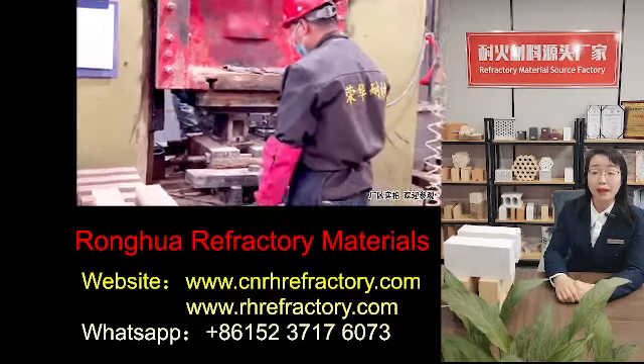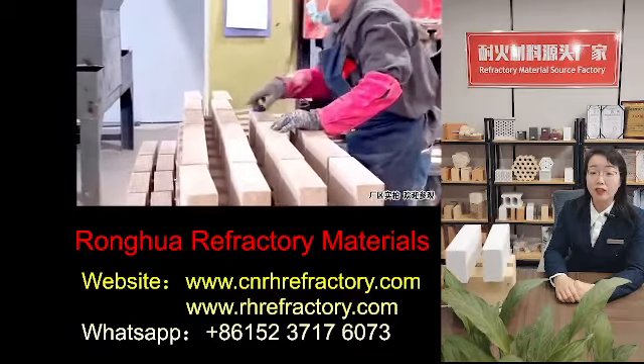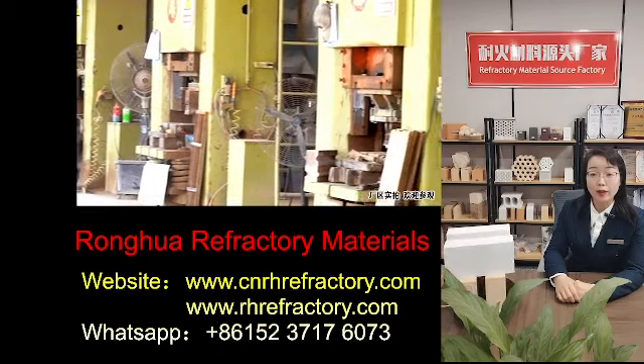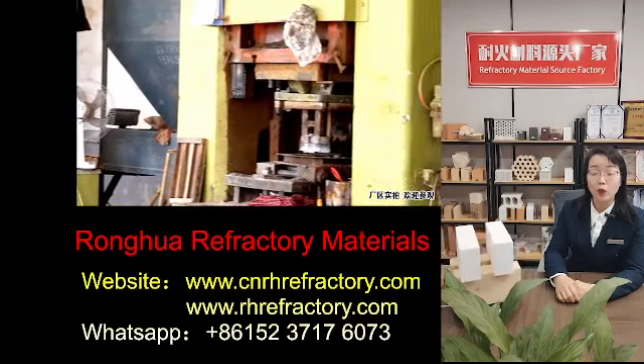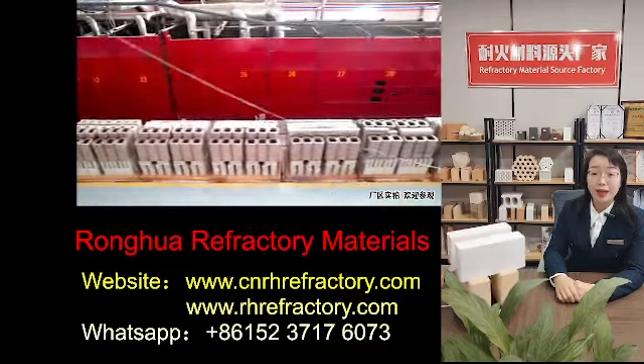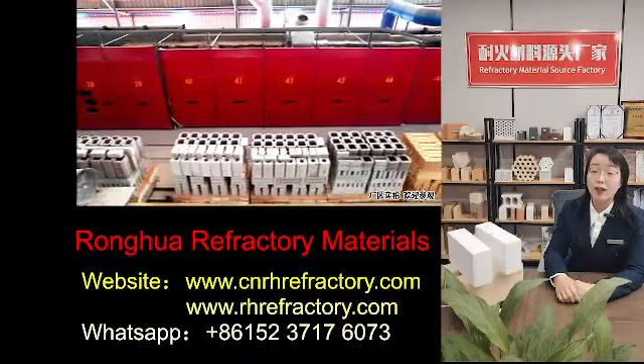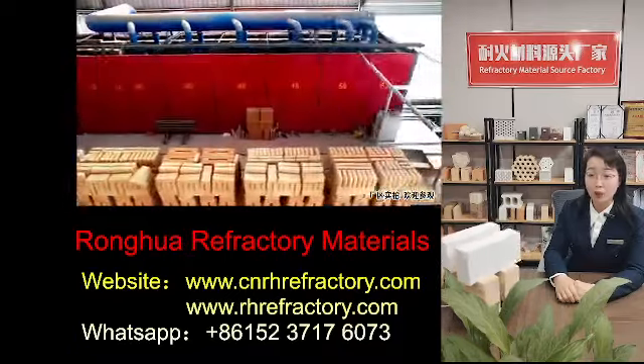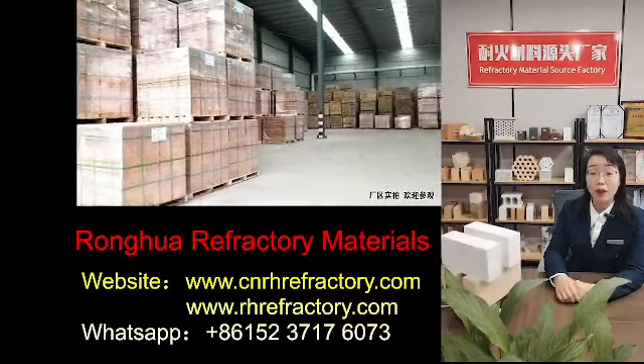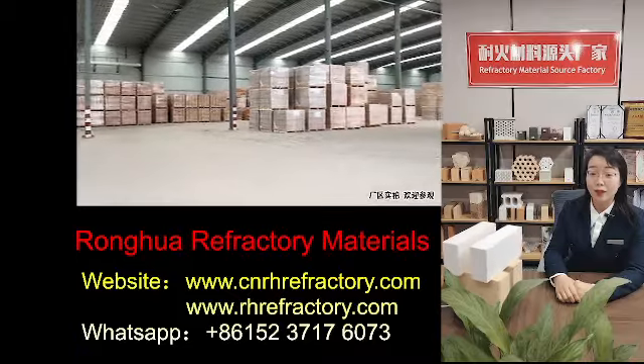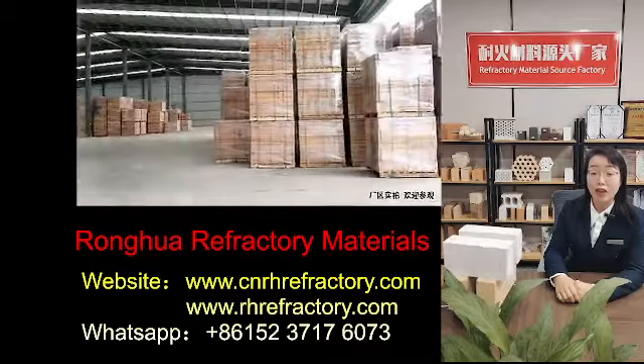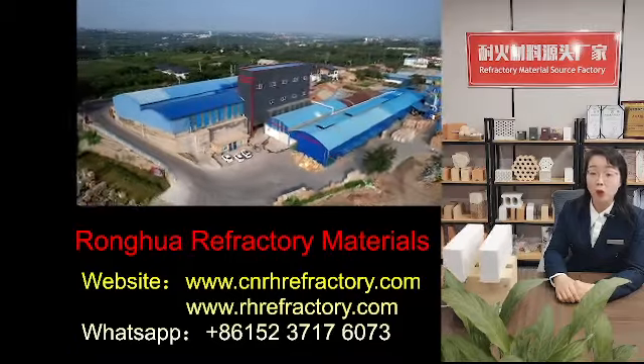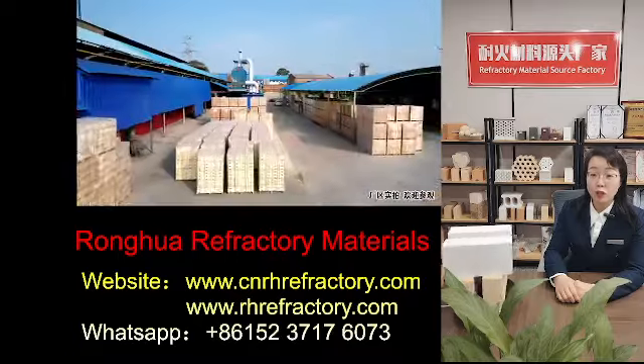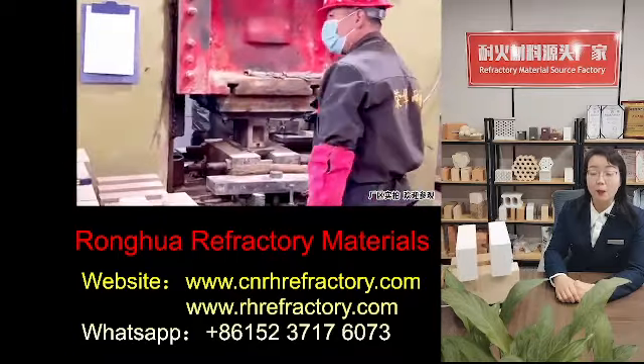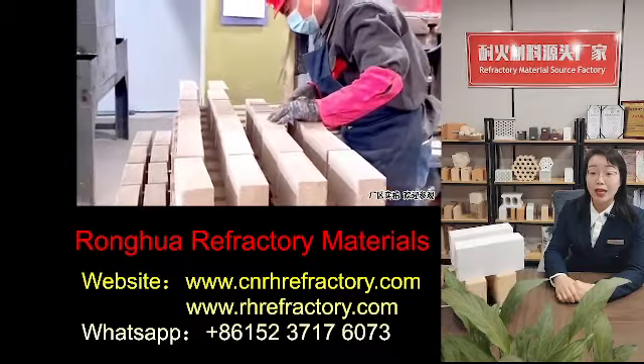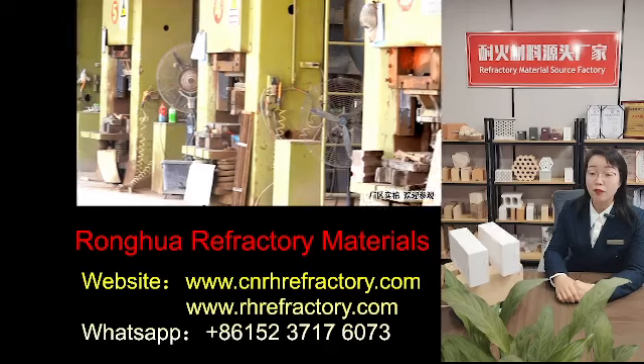The structure of silica mullite bricks is high in density, and the volume density is generally 2.7 to 3.0 grams per cubic centimeter. Since silica mullite bricks have excellent density, strength, and wear resistance, they are widely used in cement rotary kiln, secondary firing part, filter part, and other parts. In addition, silica mullite bricks have high refractoriness under load, and good high temperature performance. The refractoriness under load of silica mullite bricks is above 1450 degrees Celsius, and the highest can reach above 1650 degrees Celsius.